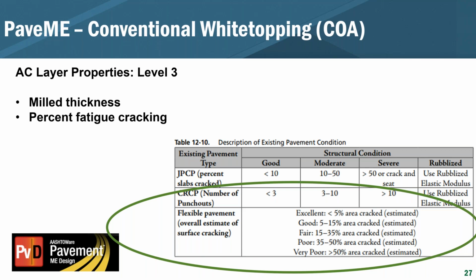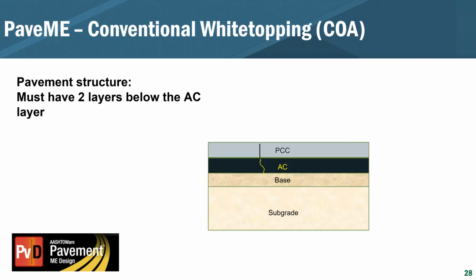Again, the big thing about this is it's critical in differentiating the stiffness of that asphalt. We're going to develop our master curve, and then based on the amount of fatigue cracking, we'll have a certain amount of damage imposed on that asphalt mixture, which will reduce the stiffness of that asphalt. How much it reduces is a function of the percent fatigue cracking. So either you're entering it in directly, or based on these 5 categories, it's going to provide you with an intermediate value and define it for each one of those. Again, we'll get back to that in a few seconds.